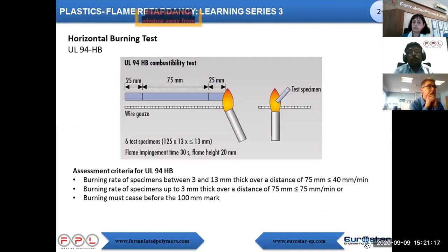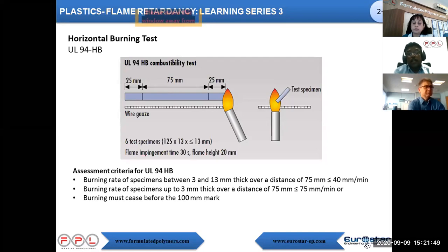Then the slide shows the HB test procedure in detail. Here in the slide you can see a specimen of length 125 mm and width 13 mm positioned in a clamp. Ignite the specimen using a burner with a blue flame. The ignition time should be 30 seconds. After the flame reaches the 25 mm mark, we need to start the clock and find the burning rate.